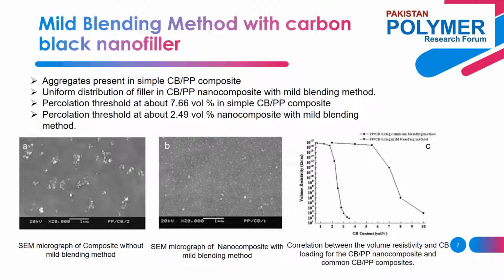Correlation between volume resistivity and carbon black loading for the carbon black and PP nanocomposite and common carbon black and PP is shown in figure C. The carbon black and PP nanocomposite prepared using the mild blending method was found to percolate at a threshold of about 2.49 volume percentage of carbon black, whereas the common carbon black and polypropylene composite had a percolation threshold of about 7.66 volume percentage. This change in percolation threshold between the two carbon black and PP composites could be explained in light of the dispersion and distribution of carbon black particles.